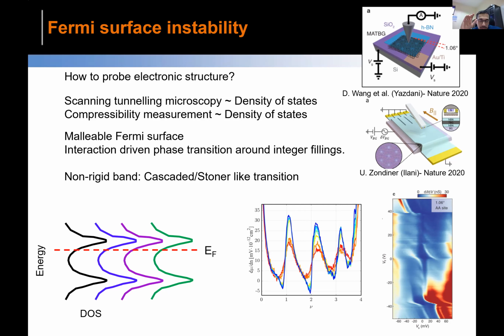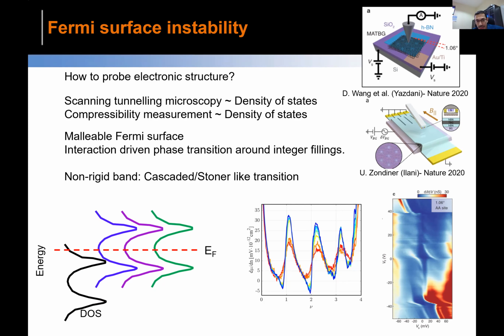That's the point. You can't do that. When you do that, everything is supposed to populate equally, right? But because of the interaction, one of them somehow becomes energetically favorable compared to the others. That is what happens during that integer filling. One of them becomes energetically favorable and gets filled up, and the others become completely empty. That is the whole point here. So you cannot design it experimentally, but because of this self-consistent interaction, as you go close to filling one, it automatically happens. But I cannot tell you which flavor gets populated first.